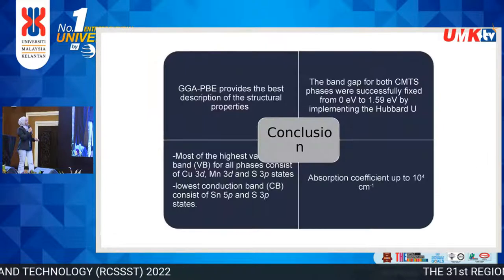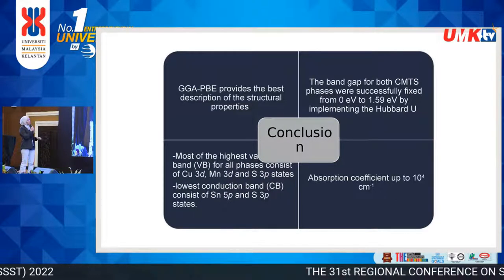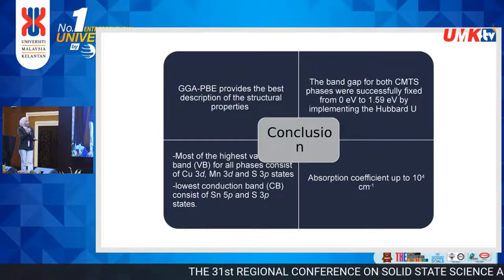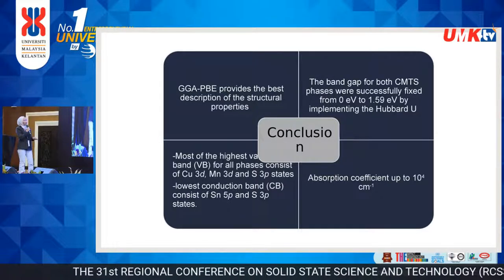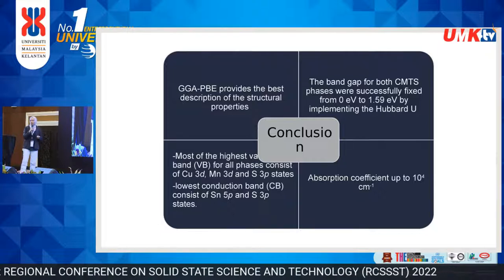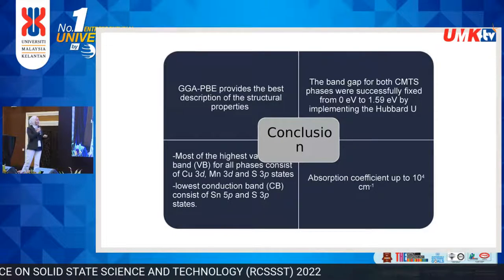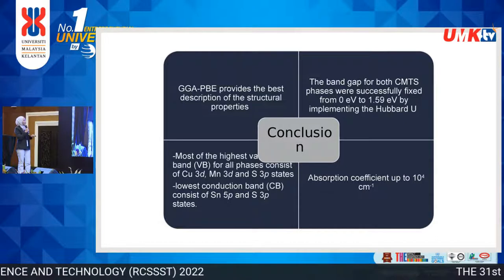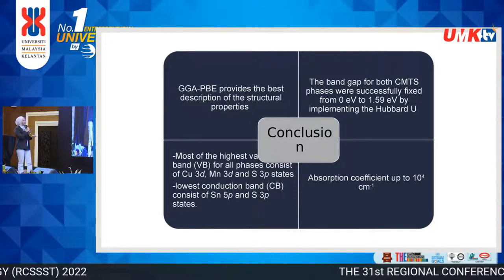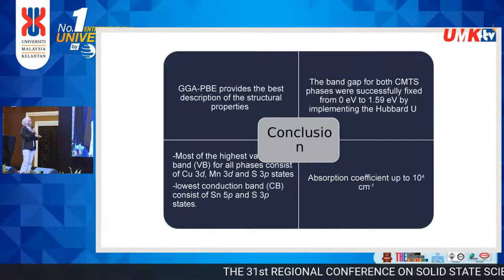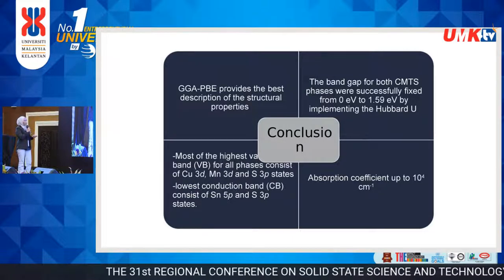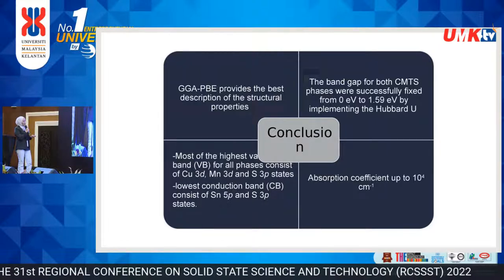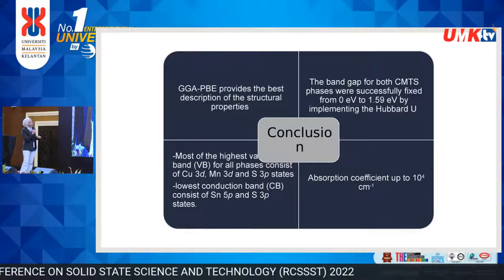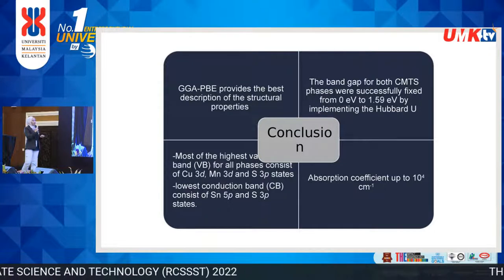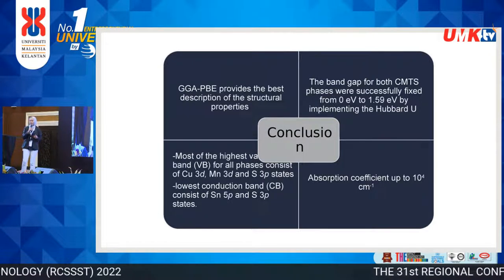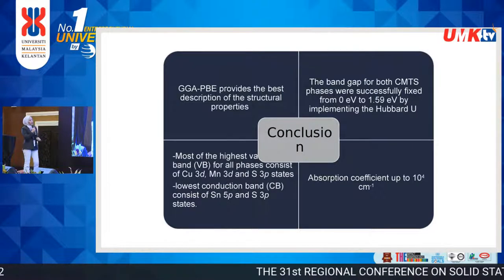So for the conclusion, the GGA PBE functional provides the best description of the structural properties. The band gap for both CMTS phases was successfully fixed from 0 electron volt to 1.59 electron volt by implementing the Hubbard U. Most of the highest valence band for all phases consists of Cu3d, Mn3d, and S3p states, and the lowest conduction band consists of Sn5p and S3p states. And lastly, for the optical properties, the absorption coefficient is up to 10 power of 4 cm negative 1. Thank you.